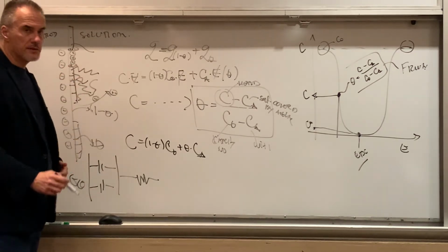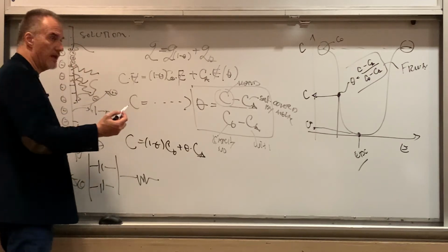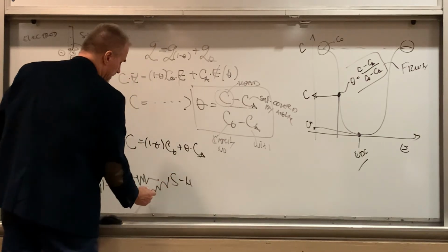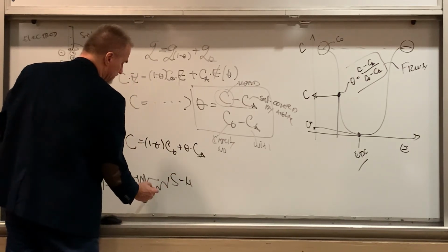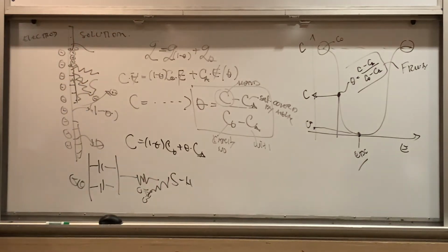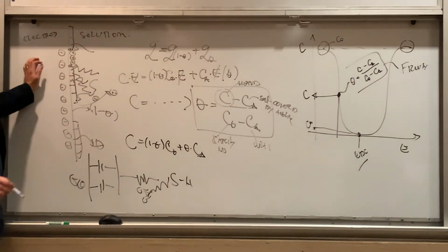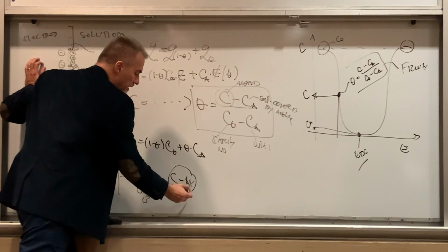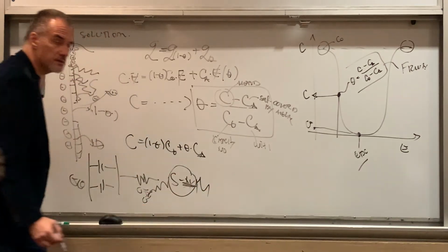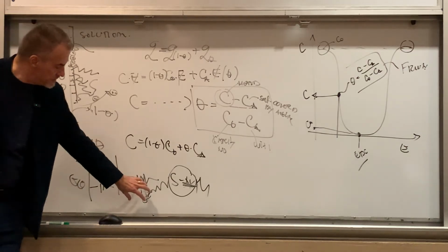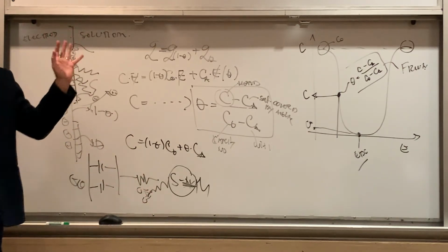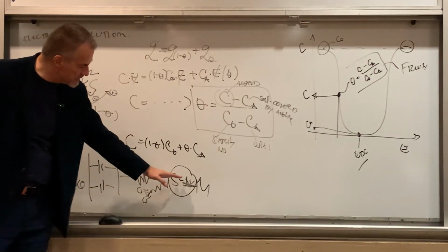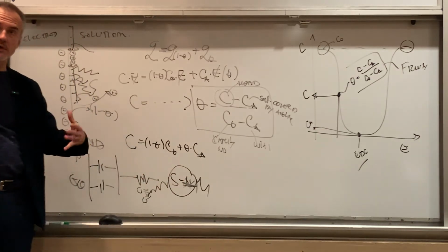It's a huge molecule, let's say MPS, mercaptan, you know, has this SH group, and then there's a propyl part, and then there's a sulfo group here, right? When this molecule approaches the surface, the adsorption happens through formation of this mercaptan, and so instead of hydrogen here, there is going to be metal surface. So this is an adsorption bond. This part of the molecule is the wetting part, which likes to be around the water. So the water molecule stabilizes this to be in solution, but this guy is bound to the surface. And it's a relatively large molecule.